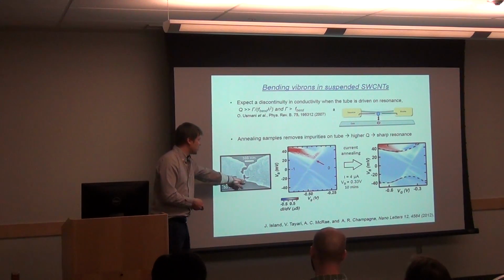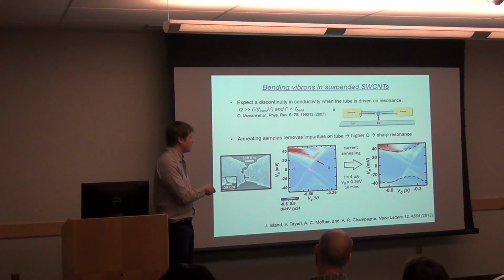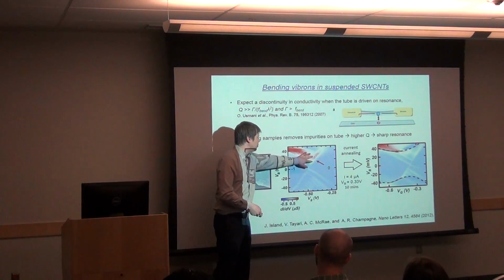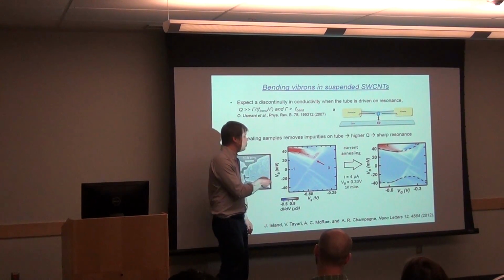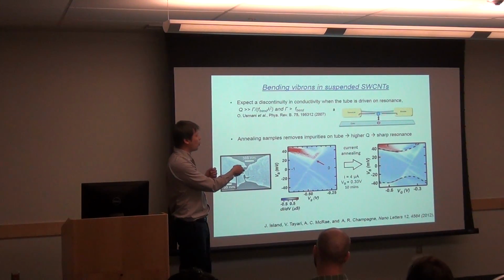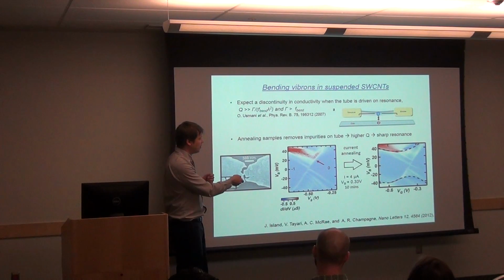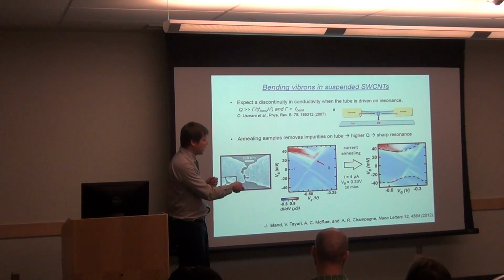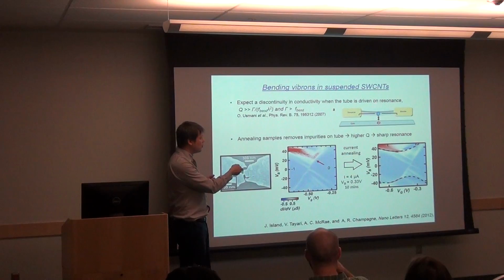And the way we monitor this is with, again, the same sort of diagrams. You can see sort of a blur here, but if you clean the system, you anneal the system, so you basically improve the quality of the oscillator, you start to see a very sharp resonance. And if you go inside the Coulomb valley, basically in this region where there's no current, the only mechanism to flow current now is to actually move this, right?